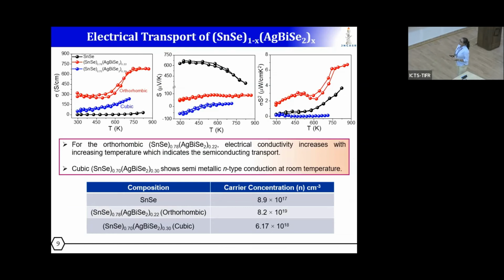Next, we have measured the thermoelectric properties. First, I'll come to the electrical transport properties. With respect to the pristine sample, both the AgBiSe2 alloyed orthorhombic and cubic samples show higher electrical conductivity at room temperature, which can be attributed to the enhancement in the carrier concentration as compared to the pristine SnSe.